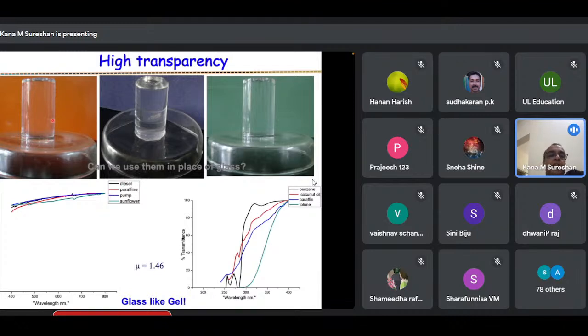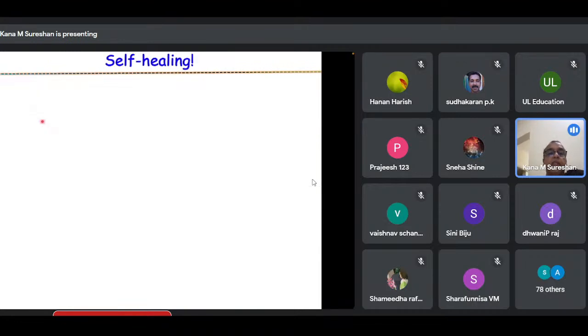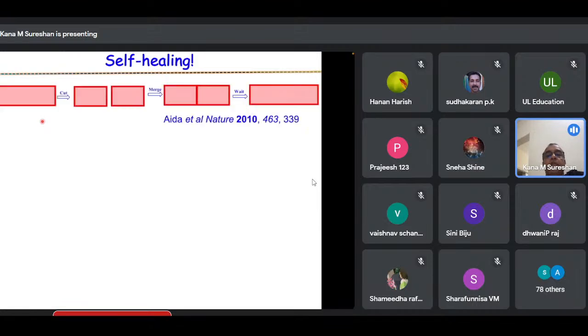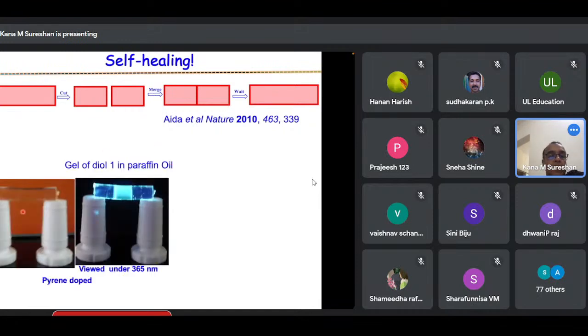But we have made gel out of oil. Oil has a refractive index similar to glass, 1.46 or 1.5. So in principle, we can use this material as a glass substitute. We can call it a soft glass because it is really soft. It is not fragile, and won't break even if it falls. Another feature we have observed for this gel is that if you cut it into two pieces and put them together, after some time you can't see the separation. So they are self-healing. It automatically heals after some time.